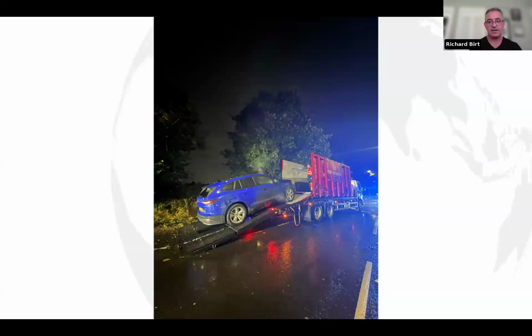What they do is they pull this unit out and the EV gets pulled into this unit, and it has a sprinkler system so it doesn't submerge it in water, which they don't want you to do, correctly. What it does is it just cools it down below basically off-gassing temperature and thermal runaway. And it has a sump pump with a filter and it just circulates water and it's cooling the cell down as much as possible. And it's like a washing machine, but it's not standing in water.